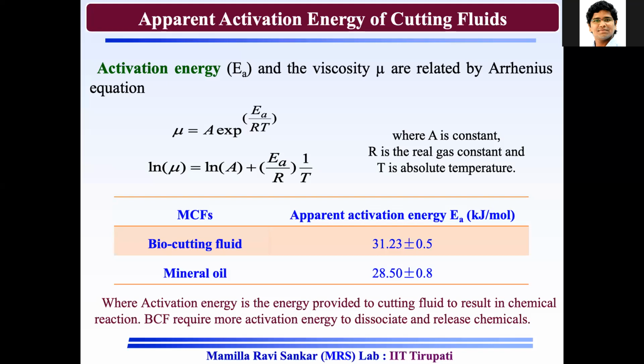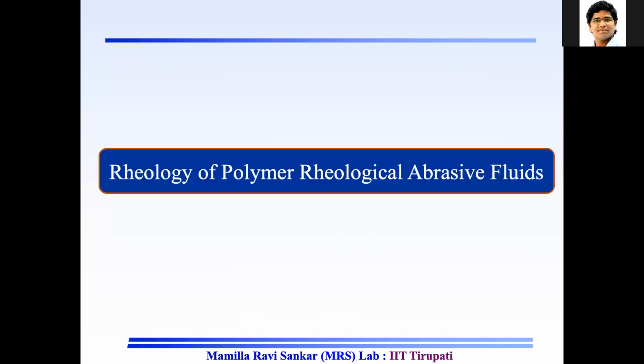From the point of emissions, which is dangerous, you have to understand two angles. One is that dangerous gases are going to evolve at a low activation energy for the mineral oil. But the biocutting fluid that we have developed and used requires more energy to dissipate and give off gases. However, the green cutting fluid has a better composition, so there won't be much danger from the point of gases.